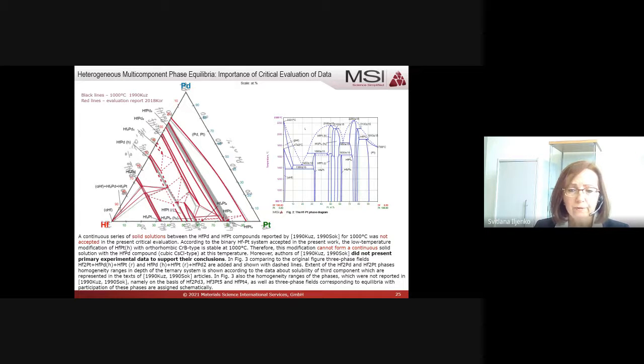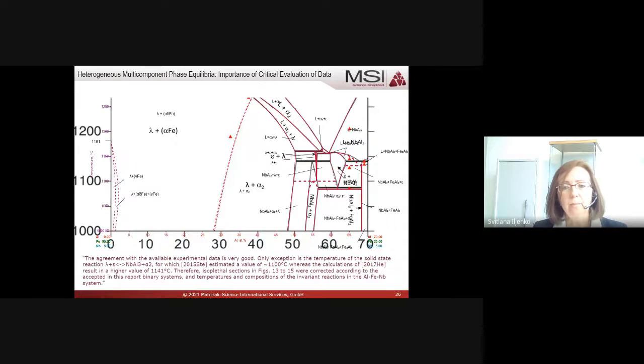What our authors also highlighted is that the authors of this original publication, this gray phase diagram, did not present primary experimental data to support their conclusions about the existence of the continuous solution here. And that means that indeed there were no data, just a ready result. So they have the same structure. We believe they have a continuous series of solid solution. If they had experimental data, that would make the job of our authors easier. So let us look to the next example.